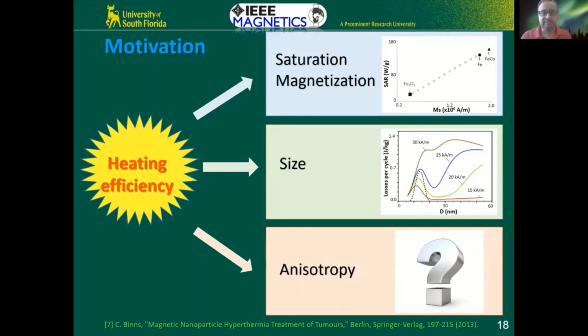These are the things that we were interested in my lab. A few years back when we started this work, we found that not many magnetic hyperthermia groups were looking at anisotropy. They were just getting commercial samples, commercial particles, and doing the experiments. We thought that we could improve this by making a careful study of anisotropy and the role it plays in improving the SAR.